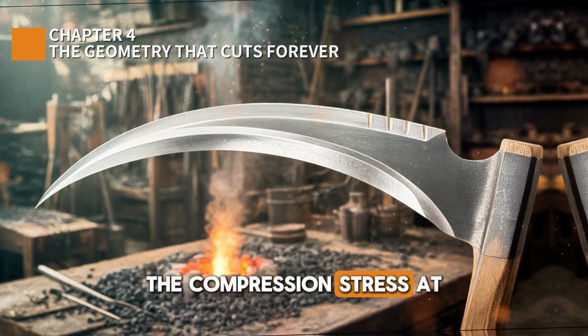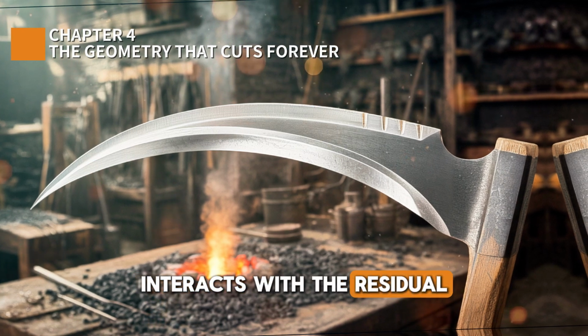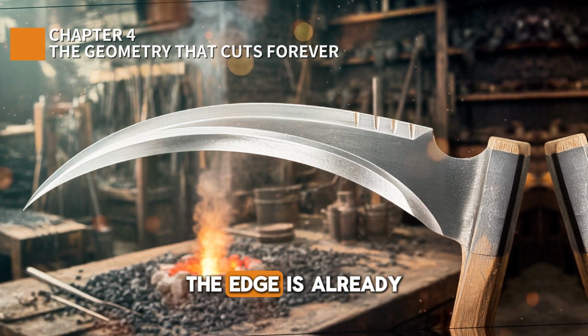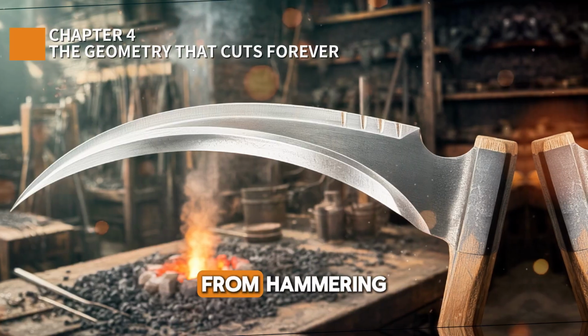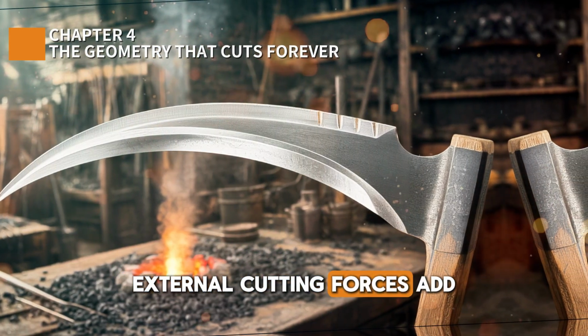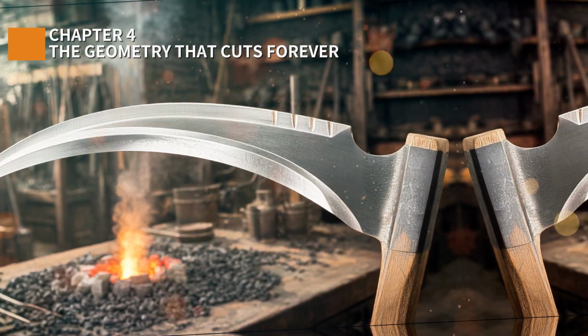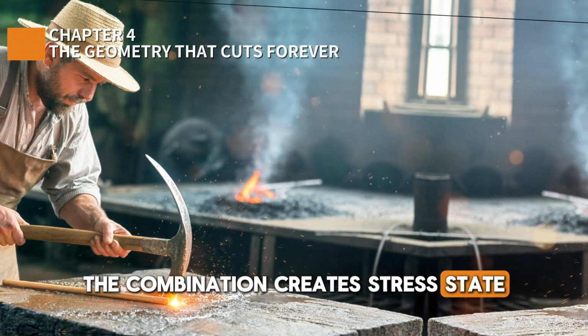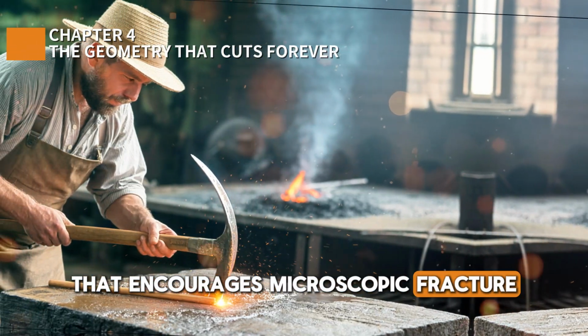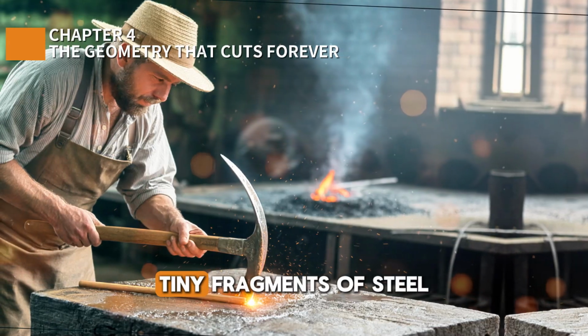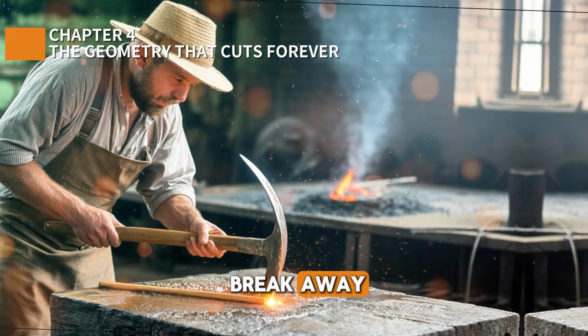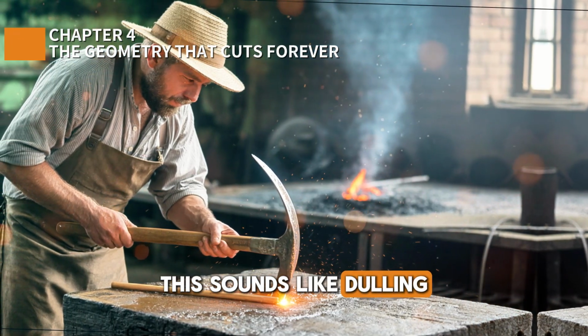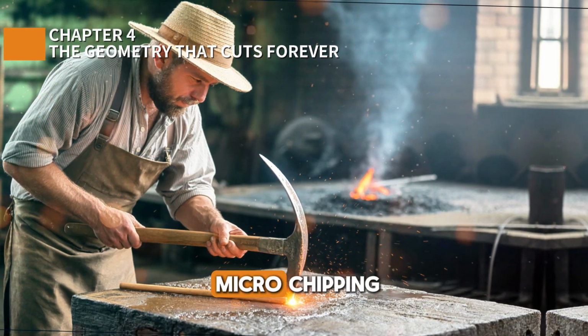The compression stress at the edge interacts with the residual stress from peening. The edge is already under internal compression from hammering. External cutting forces add to this compression. The combination creates a stress state that encourages microscopic fracture of the edge apex. Tiny fragments of steel break away. This sounds like dulling, but it's actually controlled microchipping.